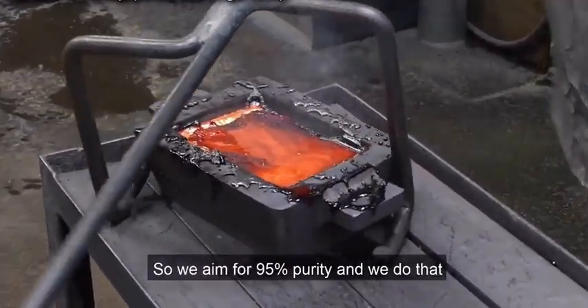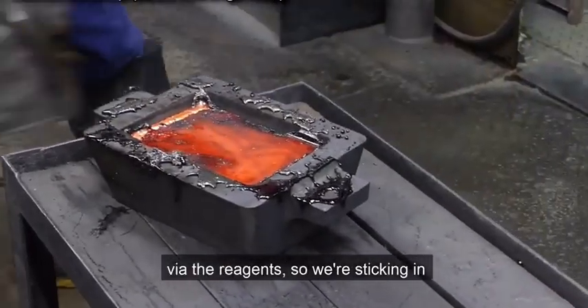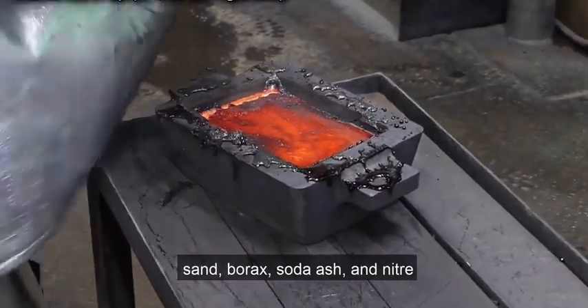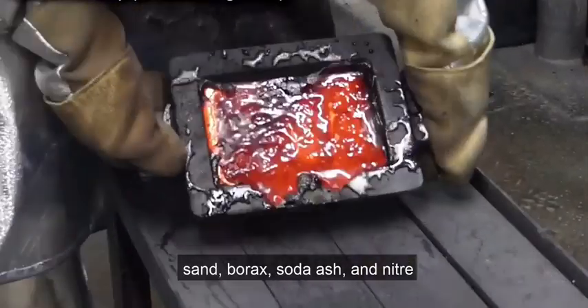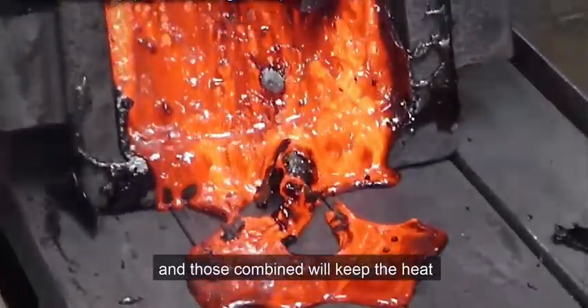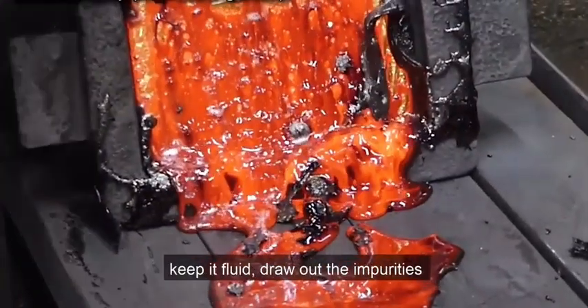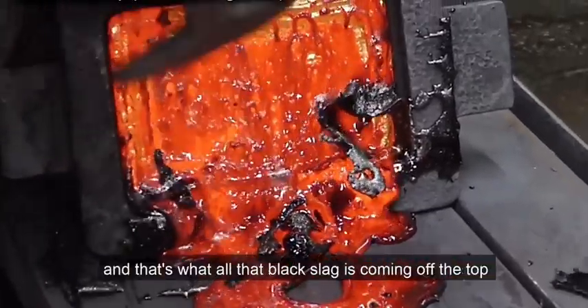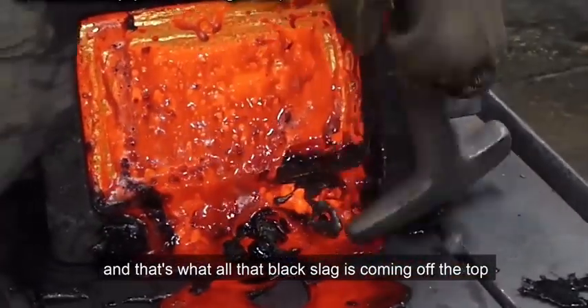So we aim for 95% purity, and we do that via the reagents. So we are sticking in sand, borax, soda ash, and niter, and those combined will keep the heat, keep it fluid, draw out the impurities, and that is what all the black slag is coming off the top, so it is not gold, it is black like obsidian.